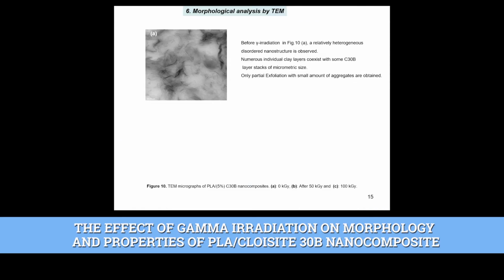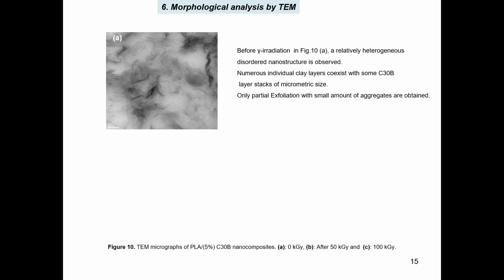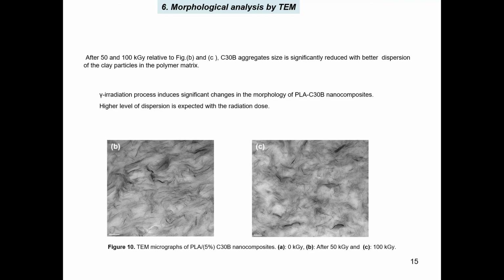And in figure 10 we have a TEM image of a PLA filled with 5% of C30B, and we can see before exposure to gamma irradiation that there is a relatively heterogeneous disordered nanostructure and numerous individual clay layers with some C30B layer stacks of micrometric size. So there is a partial exfoliation of our system. After exposure to 50 and 100 kGy, it is clearly observed that the gamma irradiation process induces significant changes in the morphology of the PLA-based nanocomposite, and consequently a higher level of dispersion is expected with radiation dose.